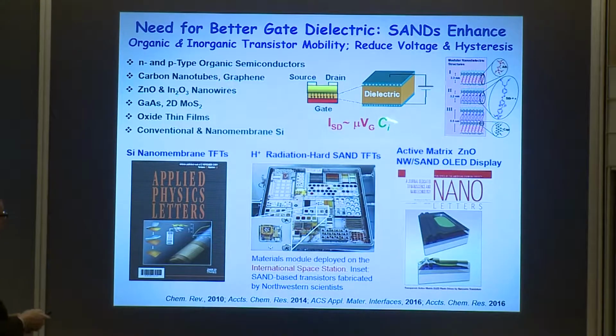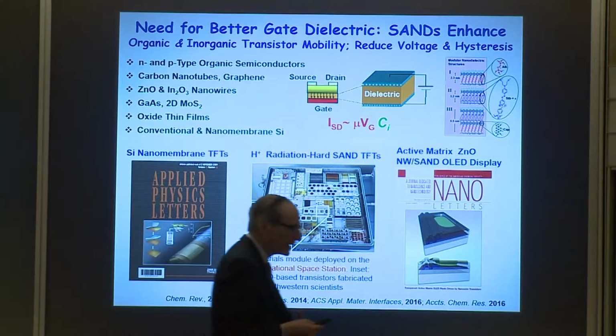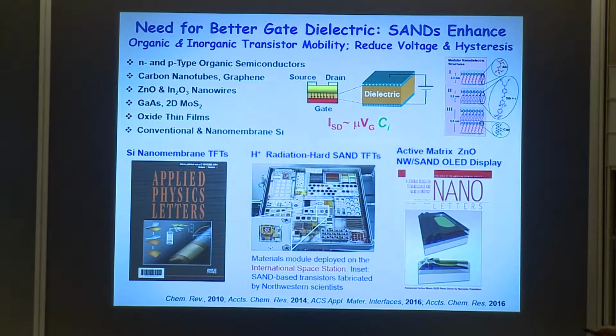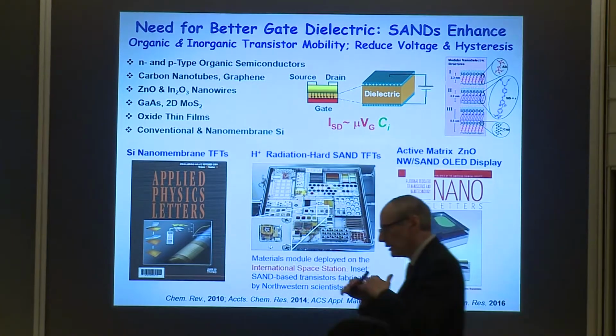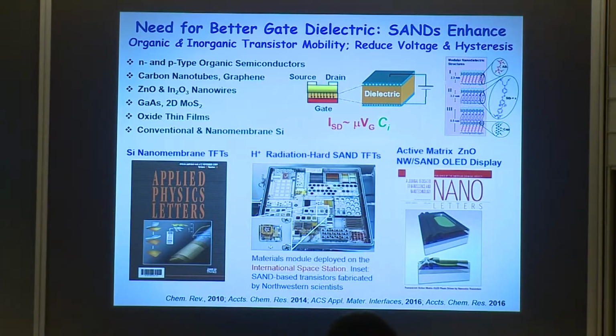So we designed some materials, I'll show more in just a minute, which involve self-assembly of different layers. They're nanoscopically thin, they have high dielectric constants, very good insulating properties, and we call these self-assembled nanodielectrics. So I'll show you a little bit more about those in a minute. But the bottom line is, to our amazement, they work very well for almost every kind of transistor material and semiconductor you can imagine. And the reason is they suppress charge. Charge trapped in this part of the transistor gives you a hysteresis, which is really bad. I'll show you that in a minute.